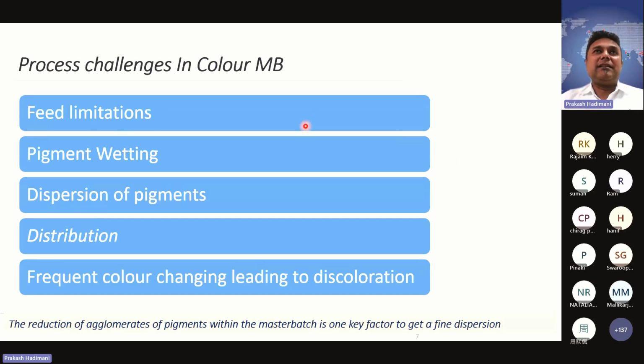What are the process challenges when you use it in the color masterbatch? Feed limitation. What does feed limitation talk about? When you premix the pigment and polymer, the pigment, meaning the low bulk density pigments, tries to settle down in your hopper, and that we call a feed limitation. We call it hopper flooding. Later, we talk about pigment wetting. You take your wax and you take your pigments, and all the wax has to be coated onto the pigments. That we call pigment wetting.